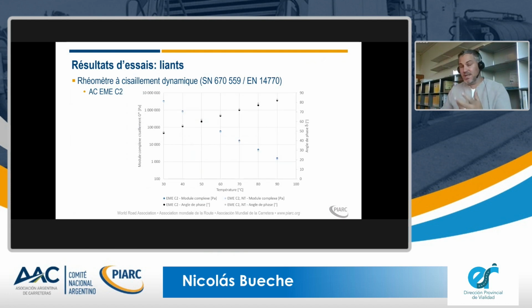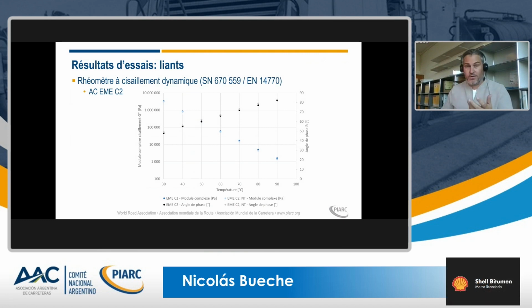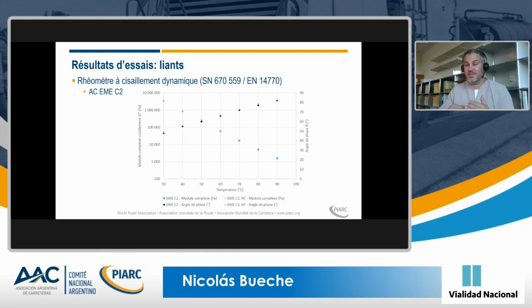If we do the same for the C2, the other high modulus asphalt, we can see similar trends, meaning that the hot mix has a bit higher stiffness than the warm mix, and the warm mix has a bit higher phase angle than the hot mix, which is quite logical, once again, if we consider this aging issue of the binder.